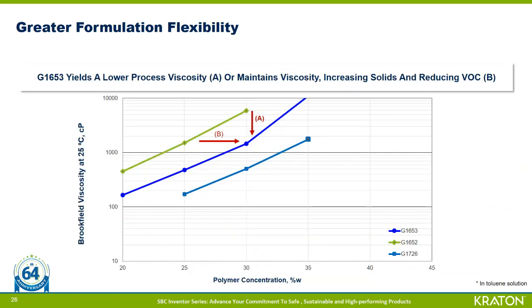The operating box for Kraton products is wide, and they can be formulated to the application needs. Here, we have an example in which our low viscosity grades may allow greater formulation flexibility compared to other traditional SEBS products, such as G1652. Two knobs can be turned to achieve performance attributes. So in this example, we have A, the polymer concentration can be maintained at, say, 30%, but then the viscosity can be lowered when we use a lower viscosity grade, such as G1653. The lower viscosity may lead to lower pressures, which may also reduce cycle times or reduce operating system costs.